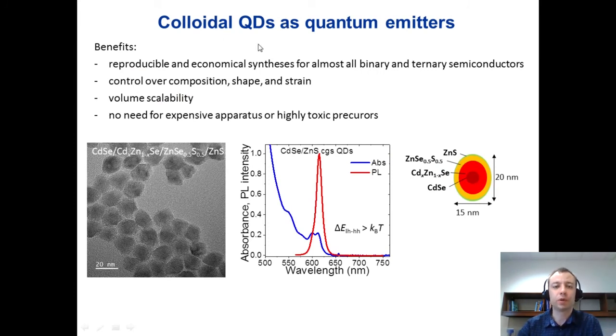The benefits of colloidal quantum dots is that they are made in reproducible economical syntheses. We have a great degree of control over their composition, shape, and strain. The syntheses are volume scalable, and there is no need to use sophisticated apparatus or highly toxic precursors. Here in my postdoctoral work, I used cadmium selenide zinc sulfide quantum dots with this complex composition, which are good candidates for single photon emitters. They emit at 620 nanometers, which is visible, which makes it convenient to handle them.